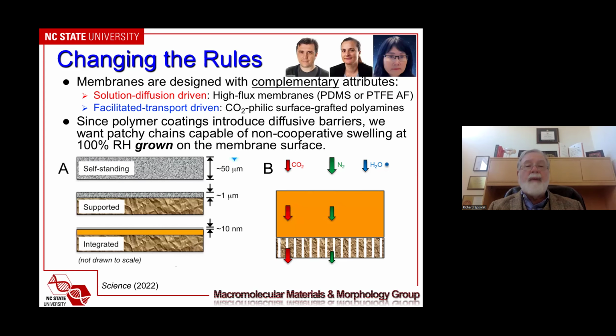Now, most polymer membranes, if they're self-standing, are about 50 microns thick. But that has been eliminated over the years such that polymer films are made much thinner, about 1 micron, but they're now supported on a macroporous support, so that when we have CO2 and nitrogen and water coming in, well, the water doesn't do anything because these polymers tend to be hydrophobic.